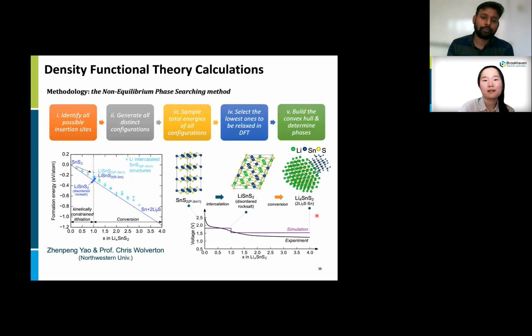This experimental data is cross-checked with density functional theory calculations. Our collaborator at Northwestern University identified all the possible phases with different amounts of lithium inside tin sulfide, and they found the most energetically favorable phases, which was consistent with our experimental observation.